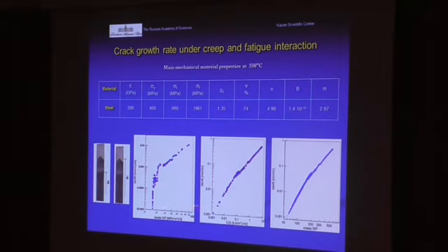In the classical form of interpretation, crack growth rate in creep conditions is a function of elastic stress intensity factor, of the C* integral, and of creep stress intensity factor.